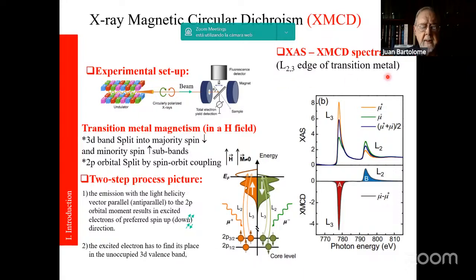Now, to illustrate this technique, I shall make use of the experiment at the L2,3 edge of a transition metal. The magnetism of a transition metal in a field can be explained in terms of its 3d band split into a majority spin down and minority spin up subbands below the Fermi energy, and the complementary empty subbands above it. Besides, the 2p shell, which is spin-orbit coupled split, has to be taken into account to understand the process.